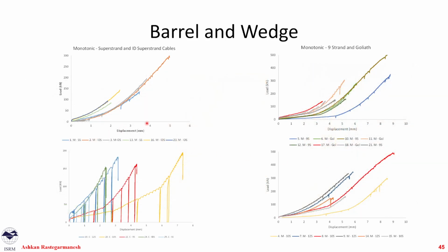The output that we got was that for different cables, we get between 5 up to around 9-10 millimeters of movement that happens during the test. Remember that for this 9 millimeters, the cable has already moved 100 millimeters. So less than 10% of the movement is actually stored in the barrel and wedge. And we realized that for cyclic testing, our barrel and wedge basically have no permanent displacement. So we have instantaneous load pickup, and we don't lose anything once our cable is unloaded and loaded.